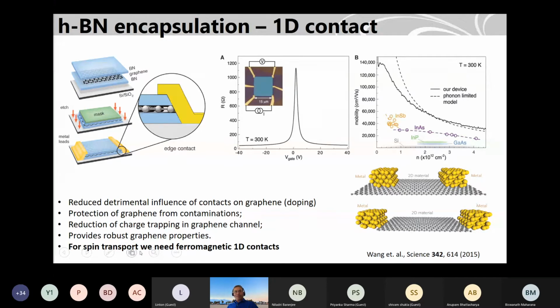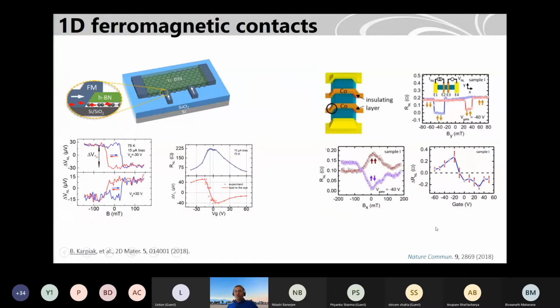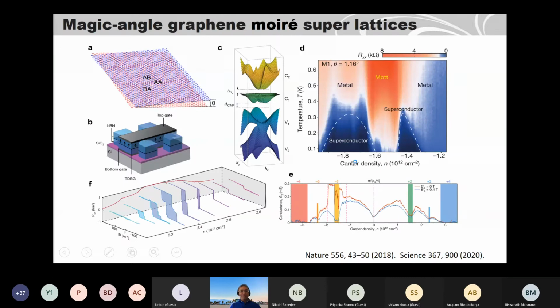So to do spin transport in graphene with high quality in the ballistic regime, what you actually need is a ferromagnetic 1D contact. These contacts before were made with chromium and gold. If you want to make spin transport, you want to make ferromagnetic contacts, but with the edges. So this is, for example, one ferromagnetic contact with the edge structure here. But what we saw was that the spin transport was a bit challenging because stray magnetic field also plays a role here. But recently some papers show that there can be some spin transport observed. But it's not very high quality graphene yet. So experiments are still going on to find such high quality graphene.